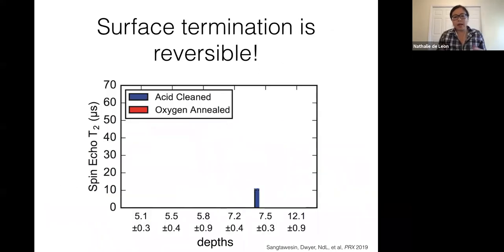Okay, so now with all of this exquisite control over the surface, what we discovered is that the surface termination is actually completely reversible and reproducible. So here is an NV center at 7.5 nanometers with a spin echo coherence time of around 10 microseconds. We can do this final oxygen annealing step to enhance the coherence time. And then we can thermally reset the surface and we see the coherence time drop again. And then we can do a final oxygen anneal to bring the coherence time back.